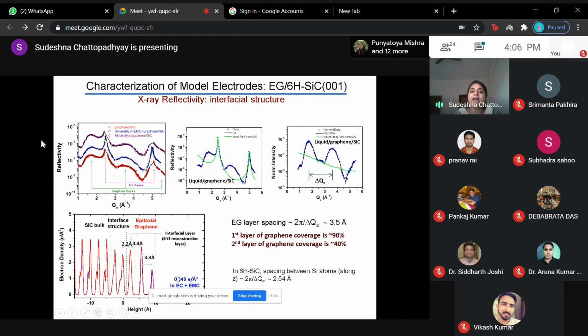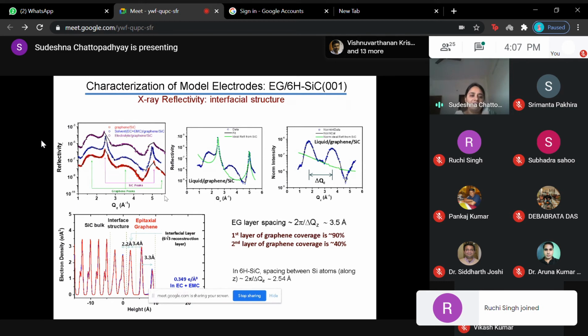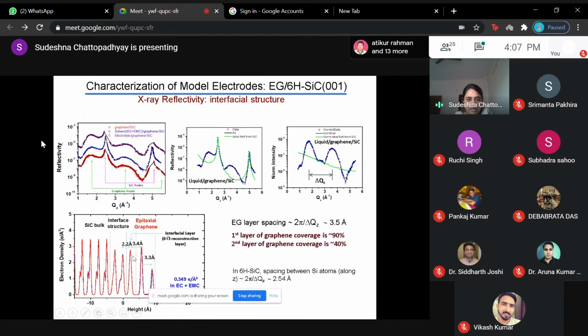But my point is that you can see the silicon carbon, the carbon silicon, separated by around 0.5 angstrom, I think. So that kind of resolution you can get. Why? Because your QZ is above 5 or 6, so the resolution is around the inverse of that, pi by QZ. So then you can get such a resolution, and then 3.3 angstrom, and as I have told, graphene